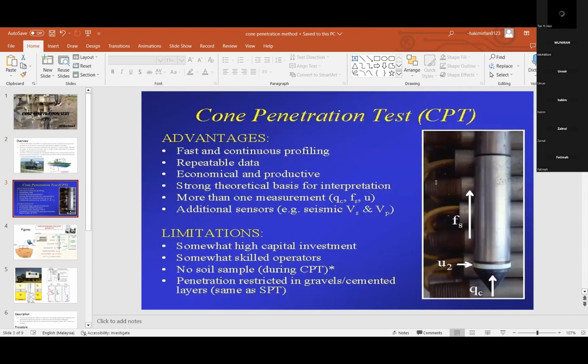The advantages of CPT are fast and continuous profiling, repeatable data, economical and productive, and a strong theoretical basis for interpretation. During the test, we get three measurements, which are qc, the measured cone resistance, fs, the sleeve friction, and u2 for water pressure. It is also portable, so we can move it from place to place. The limitations of CPT are that, although it is economical and we can use it repeatedly, it has a high capital investment and skilled operators are needed. Also, there is no soil sample during CPT, and penetration is resisted in gravels and cemented layers.